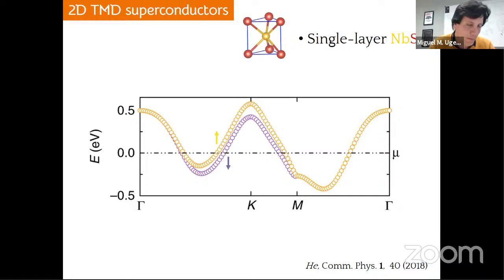Well, it's difficult to know. So there are two things regarding the spin orbit coupling. One is the fact that the Fermi surface is now spin polarized in the K pocket, right? And that triggers, for example, the Ising superconductivity in this material. And the second one is that this splitting approaches one of the subbands close to the Fermi level, and that may have an effect on the superconductivity. However, it's been estimated that the energy in this system must be around 10 milli-electron volts. So I don't think, in particular in niobium diselenide, this pocket or the onset of this pocket lies so close to the Fermi level. So in my opinion, I don't think the existence of this subband is affecting the emergence of these spin resonances.